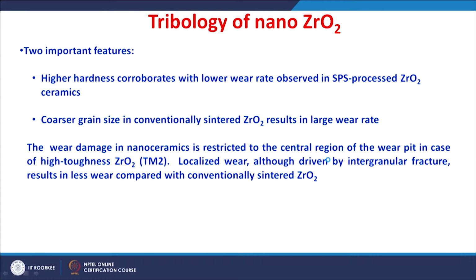There are two important features involved in this tribology. Number one, there is a higher hardness for the SPS processed zirconia ceramics compared to the conventional ceramics. The higher hardness corroborates with a lower wear rate because it will not allow the wear to happen easily. The spark plasma sintered materials always show a higher hardness because of the finer grain structure. So, the higher hardness agrees with the lower wear rate observed for the spark plasma sintered zirconia nanoceramics. The other point is the coarser grain size in conventionally sintered zirconia results in a larger wear rate.